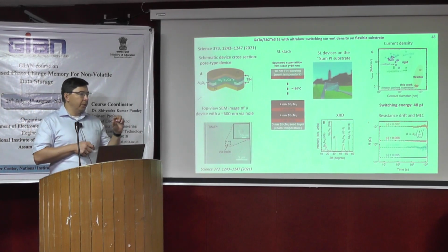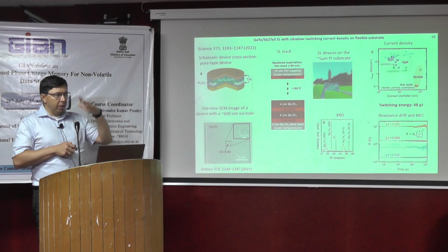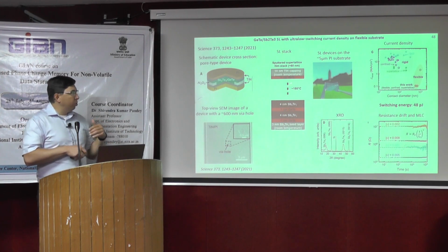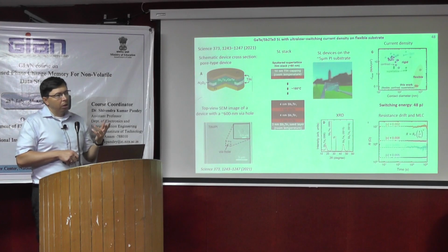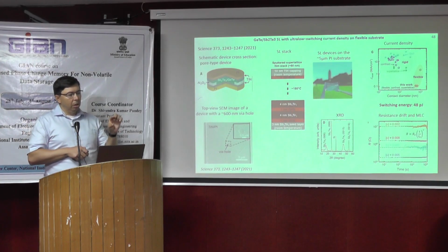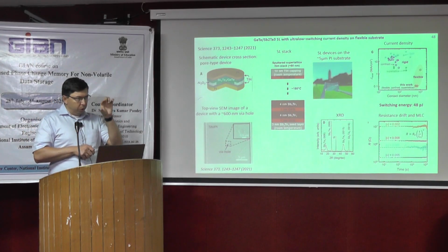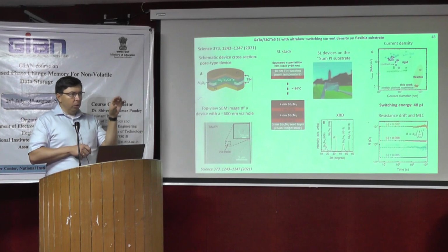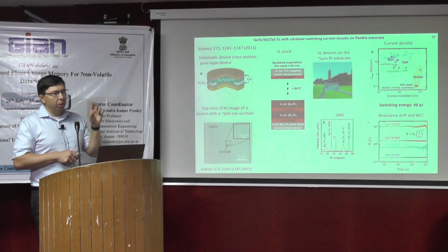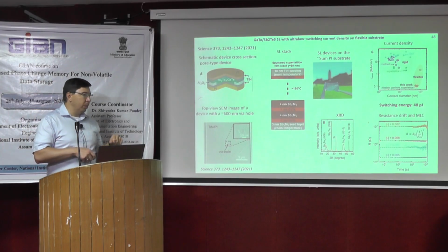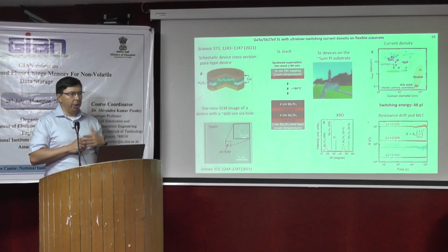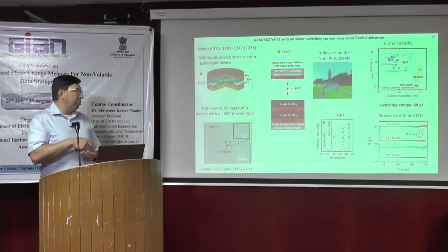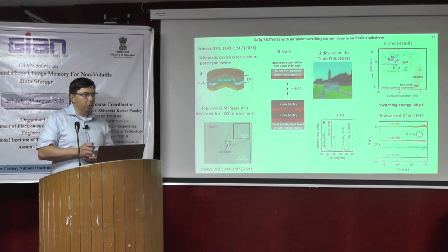If you want to increase the density, the number of these van der Waals-like gaps, you either use solely antimony telluride, but the amorphous state is not stable, or you go to GST 124. And this is also limited. It has 2 layers, 3 tellurium layers per building unit, and you cannot go down. Maybe you can find some in other compositions, but antimony telluride would be nice to have if you could stabilize the amorphous state. I think this is a nice prospect to use antimony telluride.